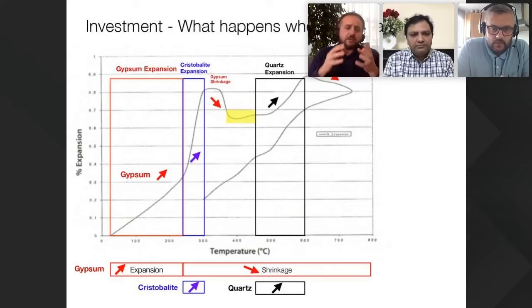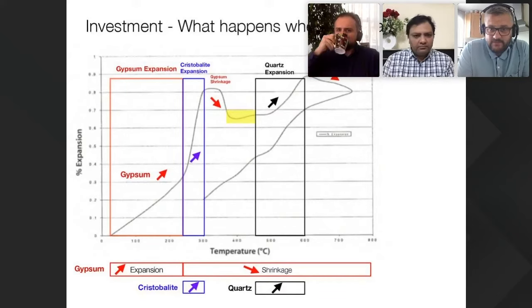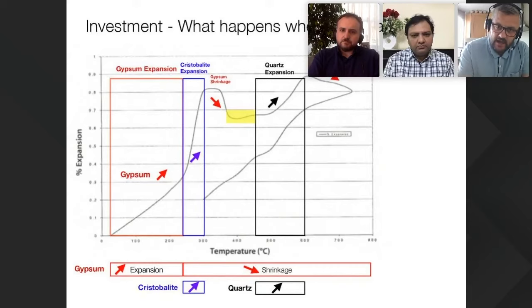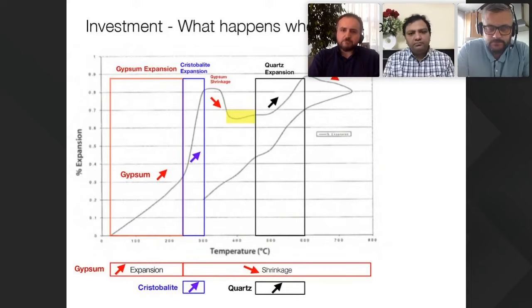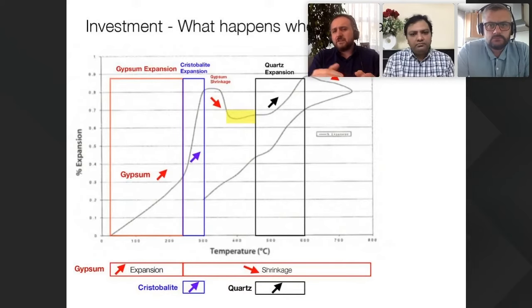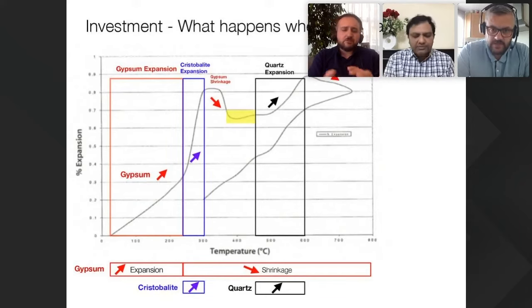You have these movements basically happening. The way that the investment powder gains its strength is when it expands more than the metal flask that it's in—that's where it gets compression and strength. So it expands more than the flask, and then when it cools down, it stays expanded higher than the metal flask is. Typically, this range is less than 1% in most investment, but I think it changes depending on the quartz, cristobalite and gypsum ratios, right? Because not all investment has the same amounts in it.